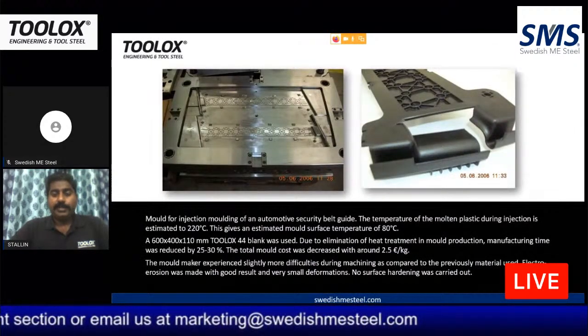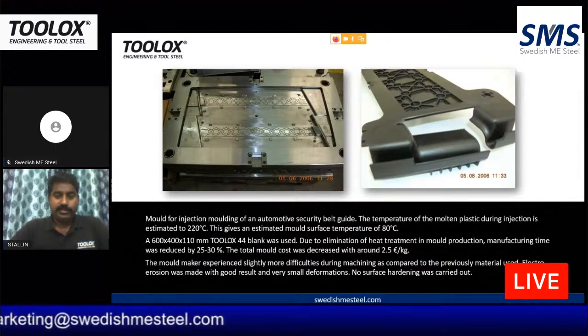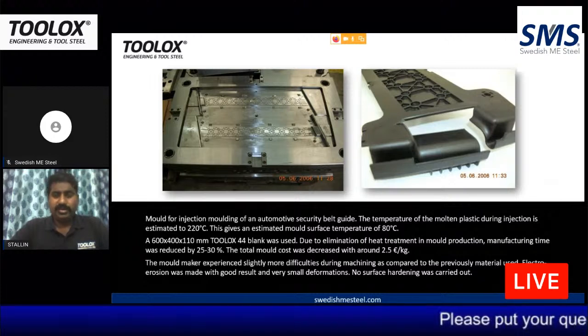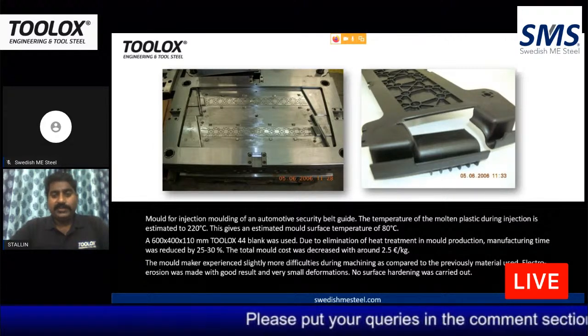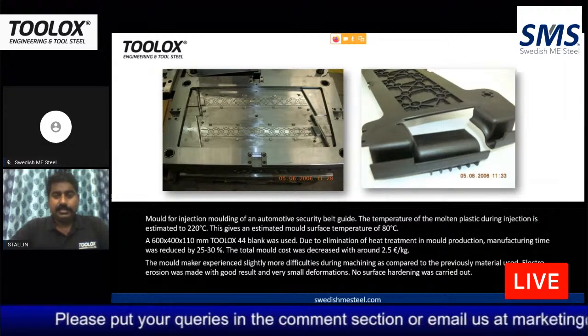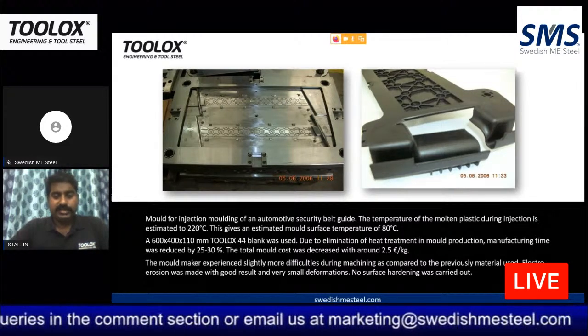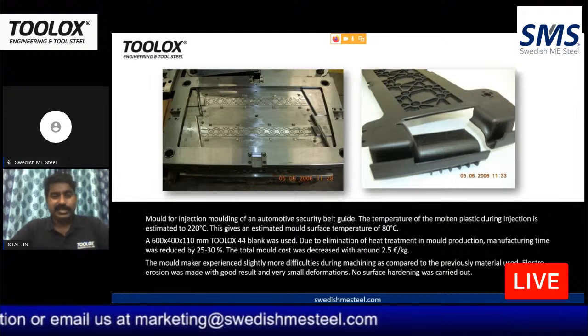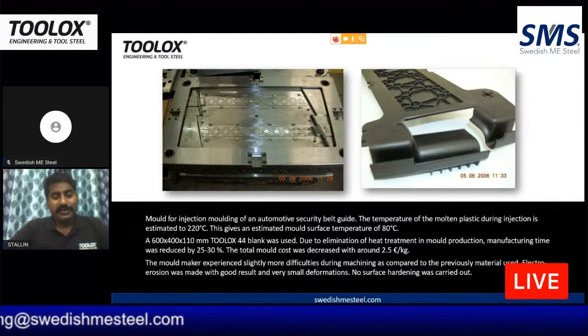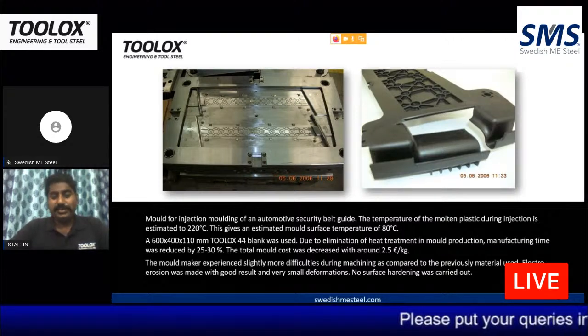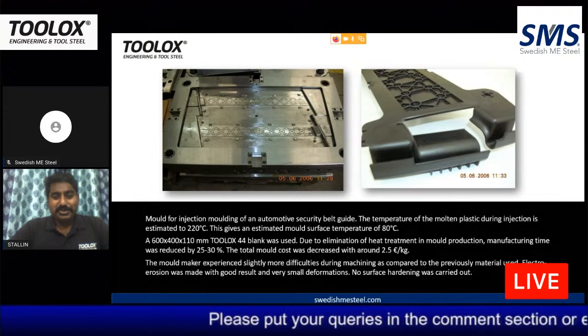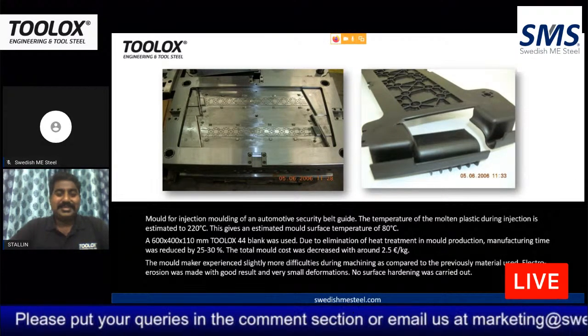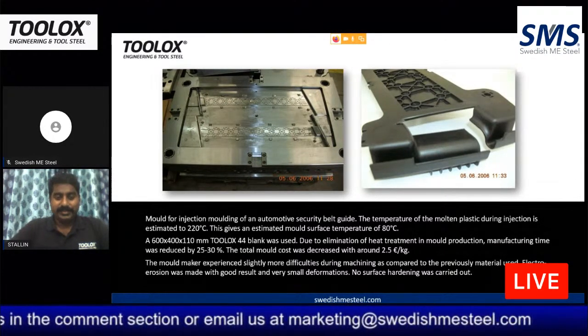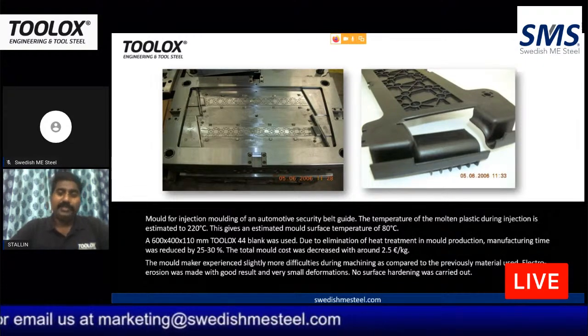So this is for security belt guides, and as you can see, the temperature of this molten plastic during injection is estimated to be around 220, and the equivalent mold surface temperature would be around 80 degrees centigrade. So there is no heat treatment here. Manufacturing time was reduced by 25 to 30%, and you can see the comment of the customer. The total mold cost was decreased by around 2.5 euros, which is around 222 rupees per kg. So there is a lot of saving with using this material. Once you start using it, you will be able to feel it.